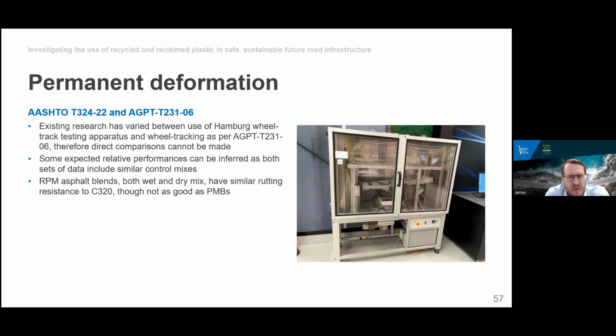But as unmodified bitumen asphalts were utilized in both sets of testing results, we can make some inferences about the expected relative performance comparing recycled plastics to some of the premium polymer modified binders. And so I guess the first thing to note is that the recycled plastic modified blends, both wet and dry mix, have similar rutting resistance to unmodified C320 modified asphalt, but not as good as some of the premium polymer modified binders. And the best performing, as you might expect, was the EVA modified asphalt. So the asphalt produced with A35P binder. Next slide, please.